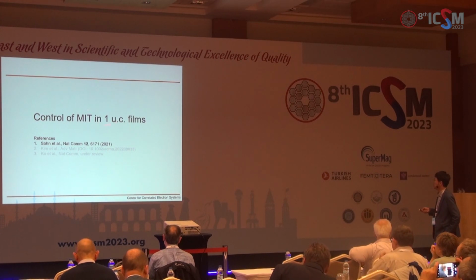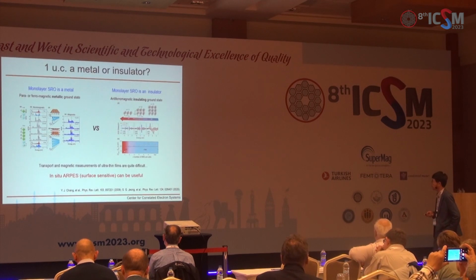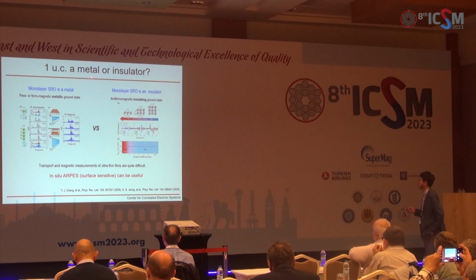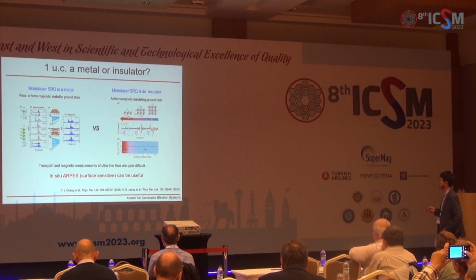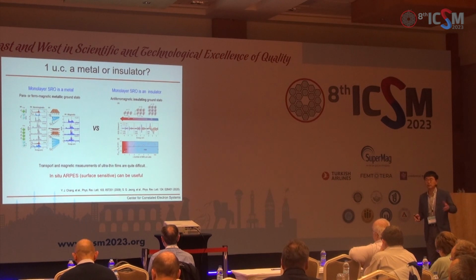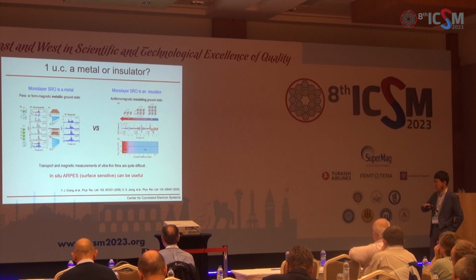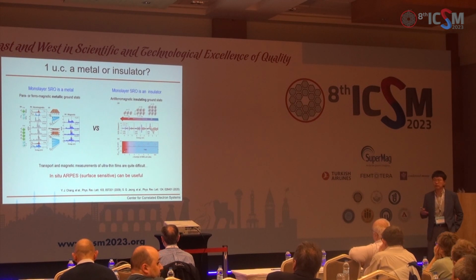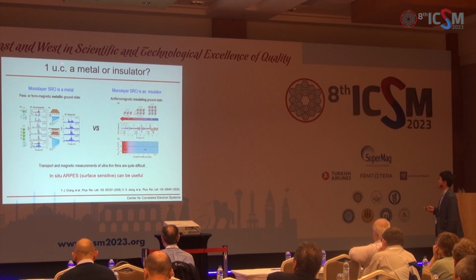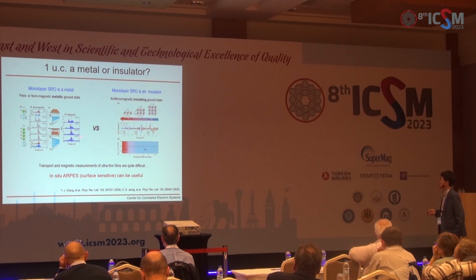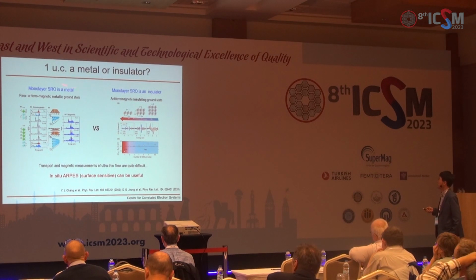Now we wanted to go all the way down to 1 unit cell of strontium ruthenate, and see what we can do here. There was an issue of whether this 1-unit-cell film is a metal or an insulator. This actually dates back to the 70s, whether these two-dimensional systems are susceptible to Anderson localization and inherently become insulators. The same issue was here, and there were recent conflicting reports. One says it should be a metal, and the other reports it's an insulator.